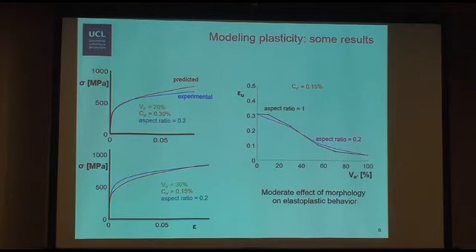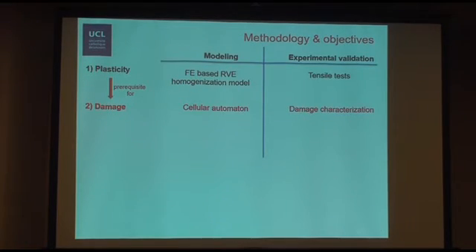But the main message I wanted to deliver with this graph is that morphology only has a minor impact, so a little bit between platelets and the aspect ratio, on the elastoplastic behavior. It's also true for prolate ellipsoids for the elastic behavior. We expect a much higher effect of the morphology on damage and fracture toughness. Alright, let's switch now to damage.